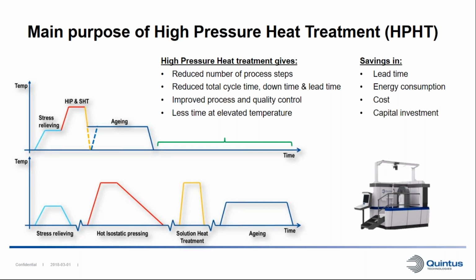If we look at the conventional way here, we might have a typical soak time in the HIP process of 2 hours. And then in the solutionizing step, we would also have probably around 2 hours soak time. So in this case, we would spend 4 hours at elevated temperature. In the combined HIP and heat treatment, high pressure heat treatment step, we reduce this time by half and we only have 2 hours at elevated temperature. And this can be quite important when it comes to limiting grain growth and stuff like that.